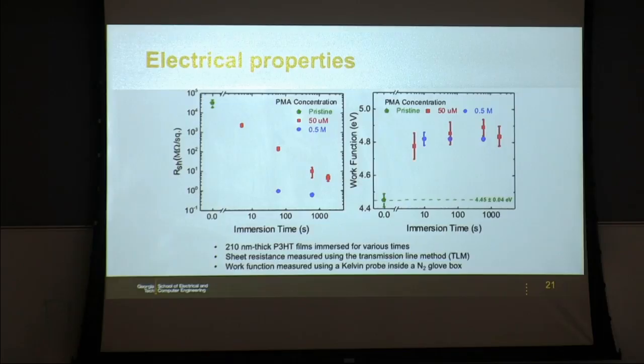And on the right-hand side, again, is an independent measurement of the work function, and you can see that the work function of a pristine film is about 4.45 electron volt. And after doping, it shifts to about 4.9, so that you have almost a 0.5 eV shift. And remember, every 60 meV, you change the density of carriers by one order of magnitude. So it's a very efficient doping.